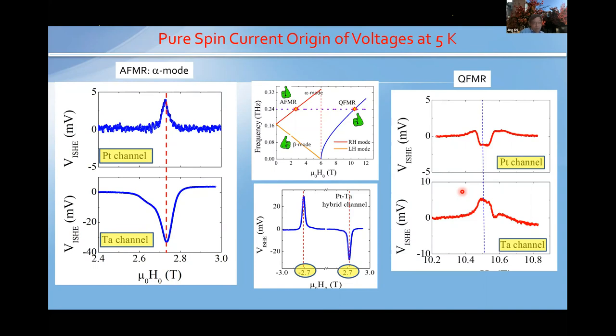to have antiferromagnetic properties. Then the detection principle here is the inverse spin Hall. It does not need a volume. It needs spin current, from the surface, from the interface. So in principle, I think it should work, but it needs to be directly demonstrated. The second part, the synthetic, I think it should work, but the resonance condition is completely different. So probably one can do this with a low frequency. That can be tried, I think. If I had a sample, I would do it.